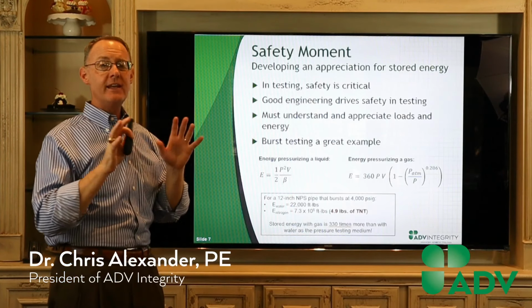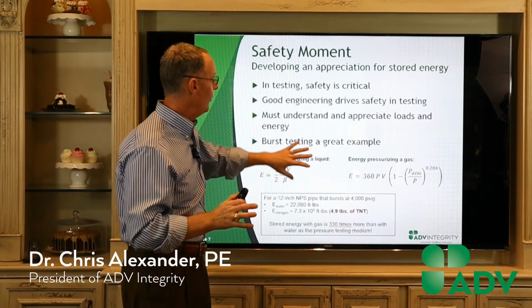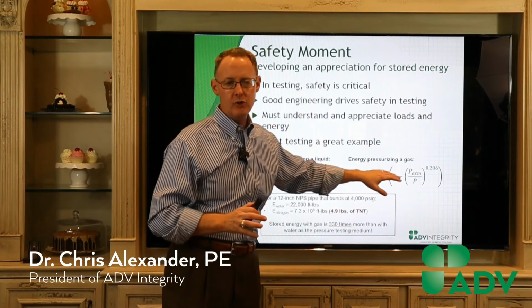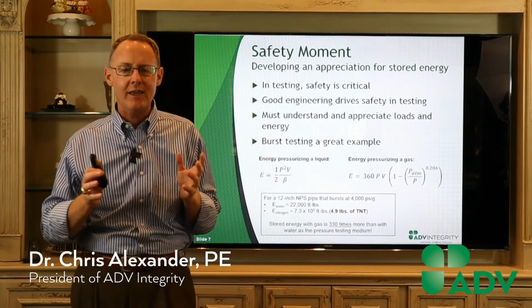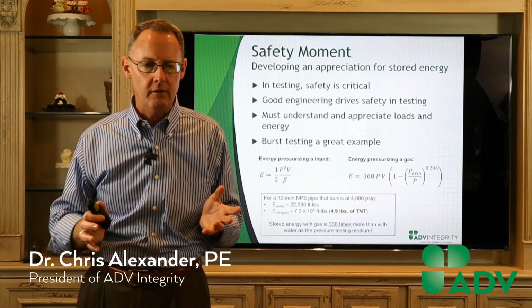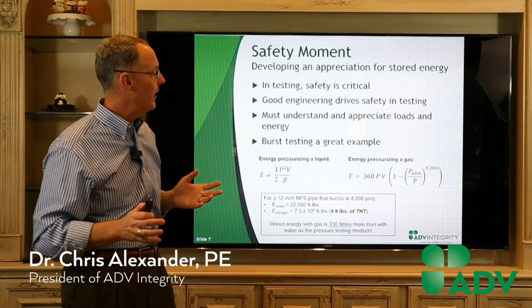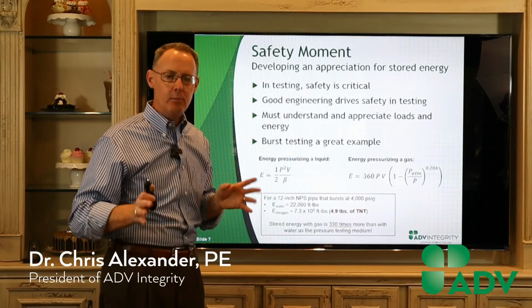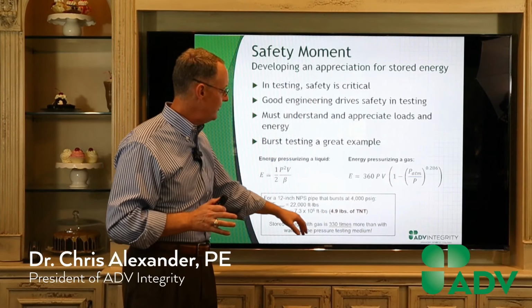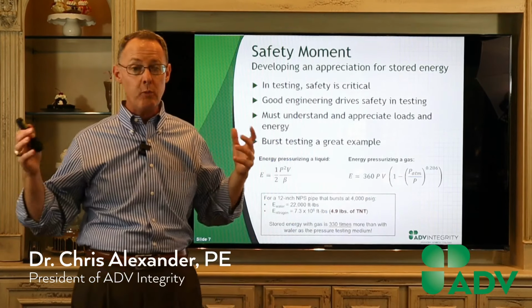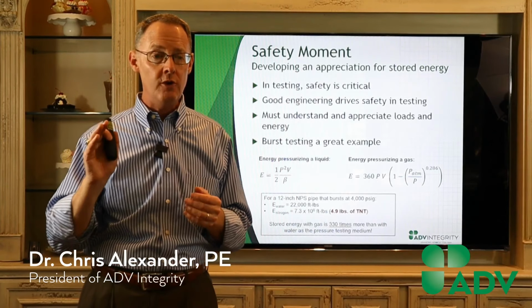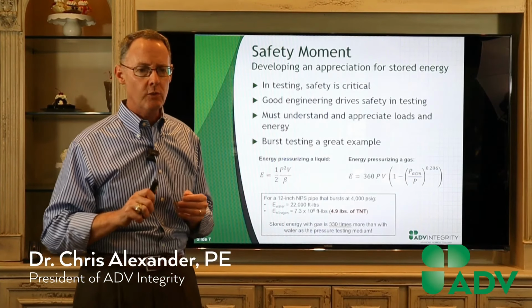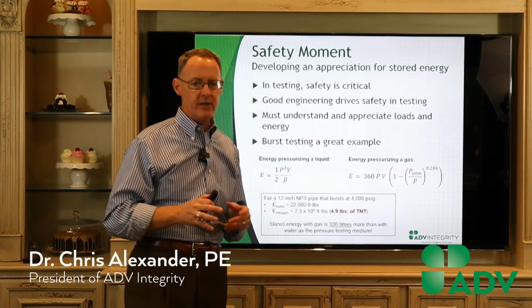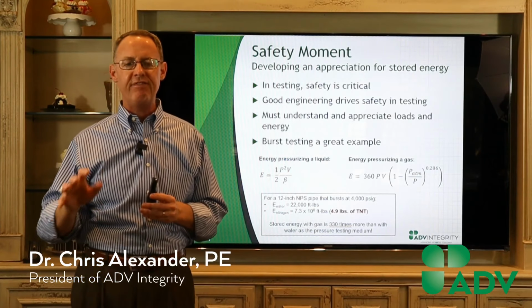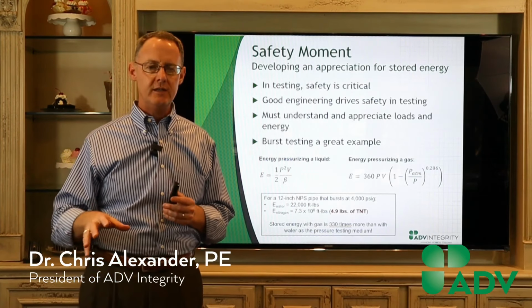Now, if I take that same sample though, pull the water out, and I stick nitrogen or stick a gas in there. Let's say nitrogen is probably the best one. I think that's probably the numbers that I ran. I do the exact same burst test. The amount of energy that's stored due to the compressibility of gas is 330 times what it is with water. And it's kind of fun to express it in terms of pounds of TNT. That's about 5 pounds of TNT.